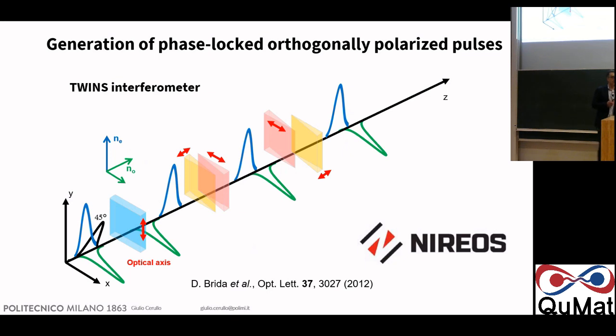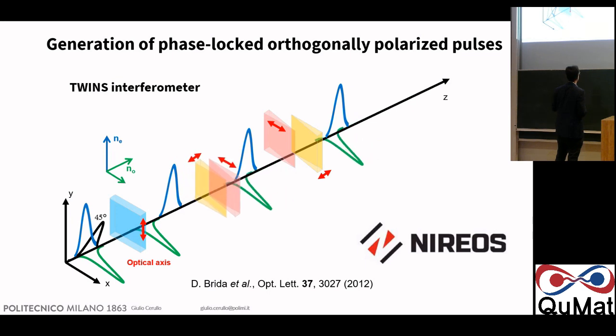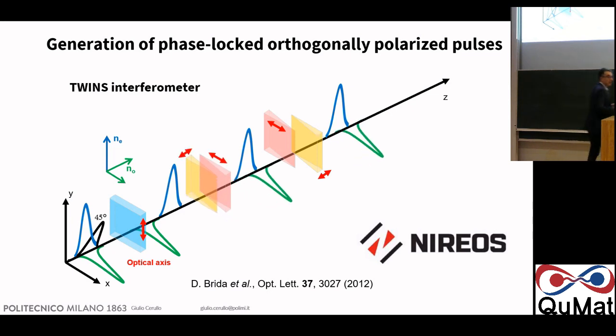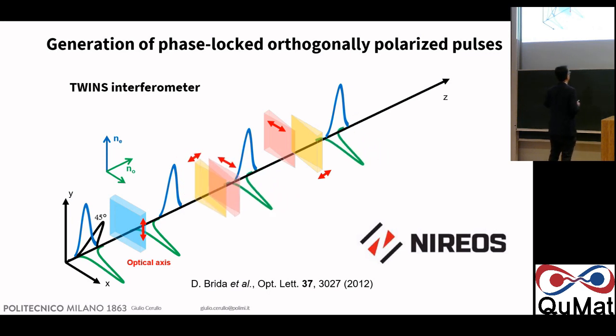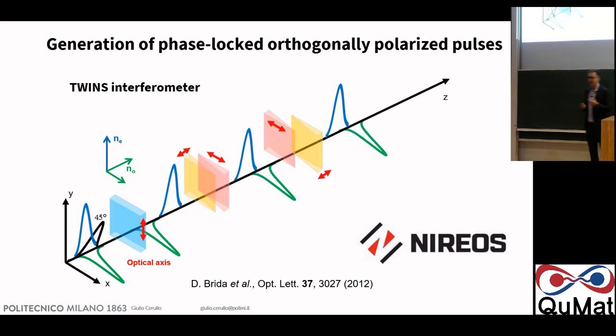We have an interferometer that we have introduced and patented for different applications of 2-dimensional spectroscopy, which we call the TWINS interferometer. And this device is based on a sequence of birefringent wedges of birefringent material. So what you do is essentially, by moving 2 of these wedges, you create 2 perpendicularly polarized pulses with really precisely controlled delay, and the delay is really parametrically stable, much better than an optical cycle. So this is the perfect instrument for testing this theoretical prediction.